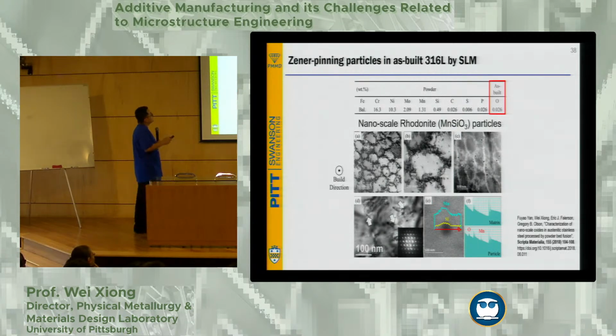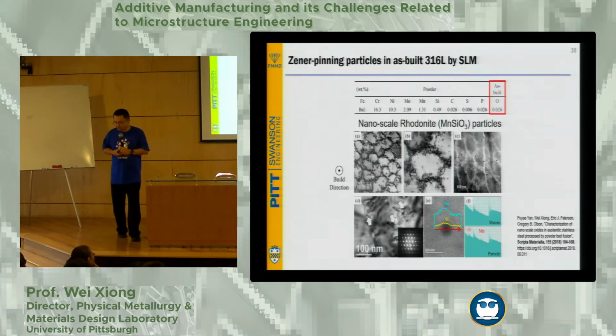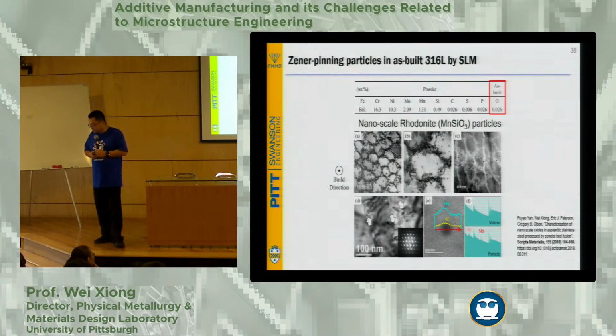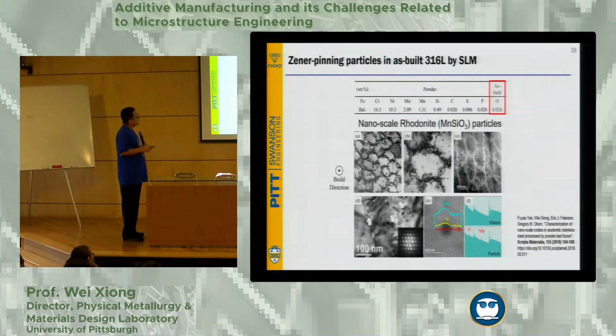We started with 3D printing of 316L. This again is a laser powder bed fusion process. We asked people to hand down some powders, we characterized the composition, and this is the composition of the material. As you can see, you have this oxygen content.